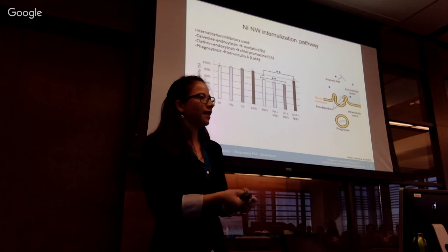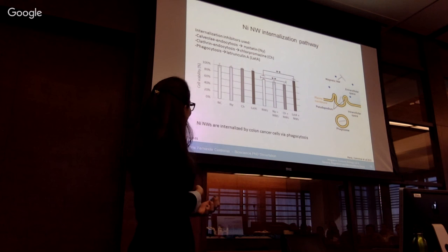So for the first two, we found that the levels remained the same, meaning the nanowires were still internalized. But for the third one, the viability levels were as the controls. So that means nickel nanowires are internalized by phagocytosis. And that is shown in the schematic here.